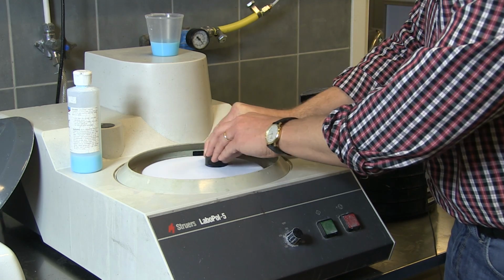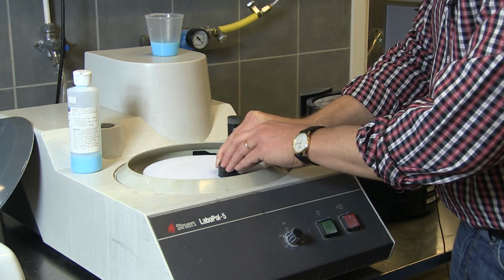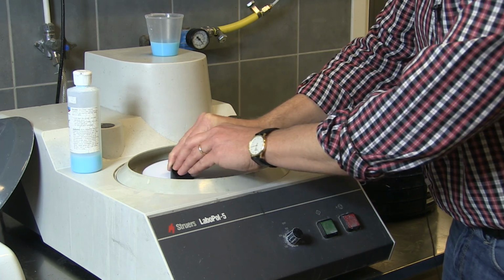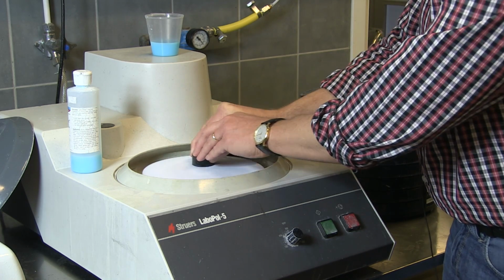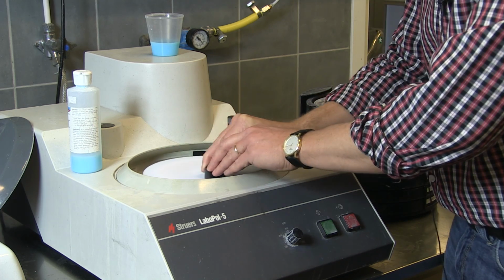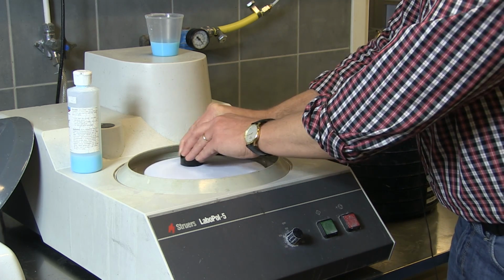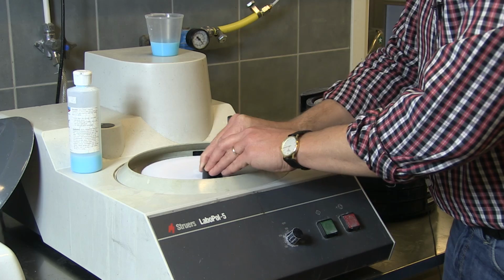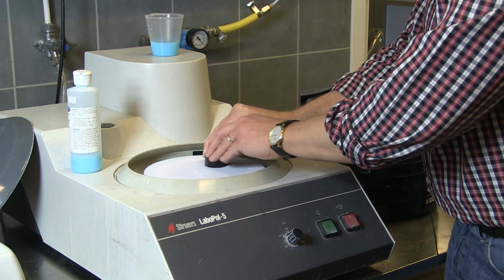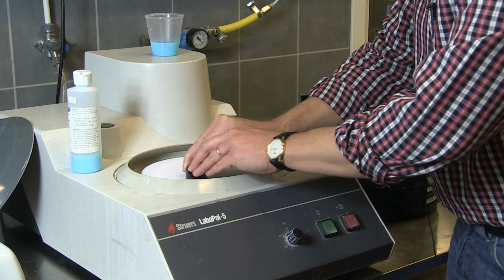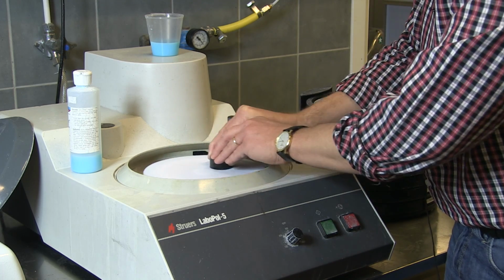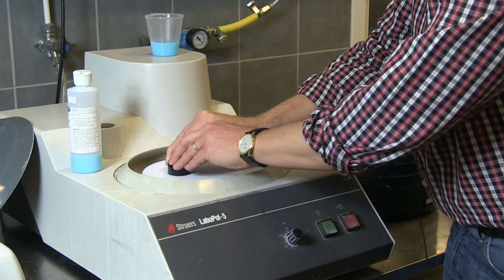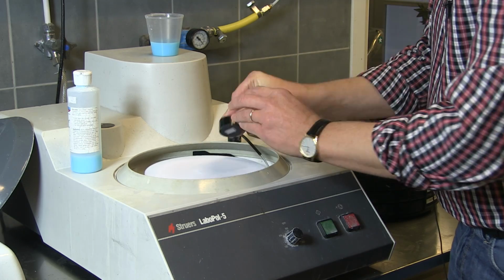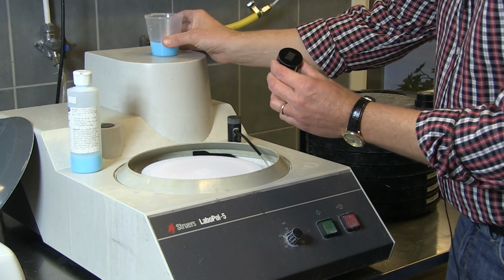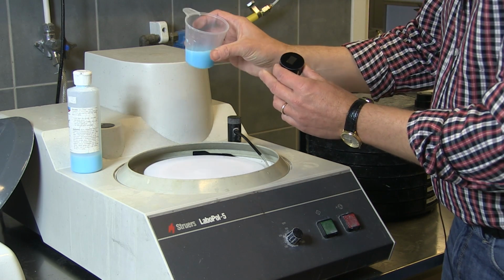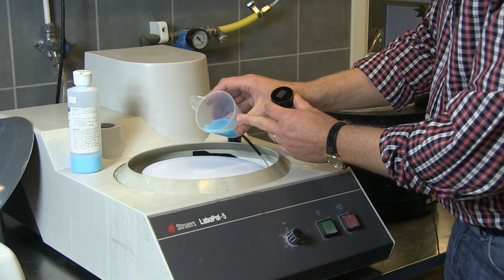As I mentioned, the cloth is a little bit napped, and even though I ground off the edge of the sample, it might grip the sample and you might lose it. You will not hurt yourself, but it will make some noise anyway, but you don't have to be scared about that. So as for diamond polishing, I move the sample around like this. I put a little bit more of the silicon dioxide suspension on.